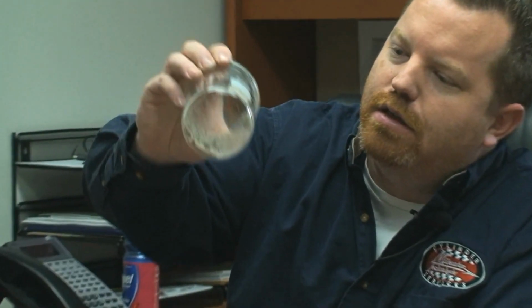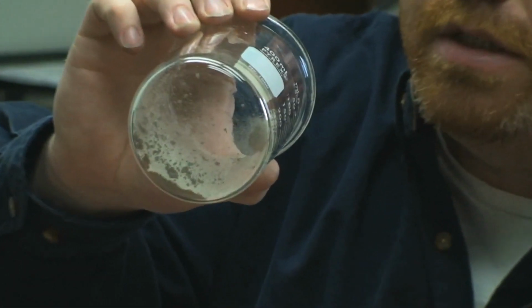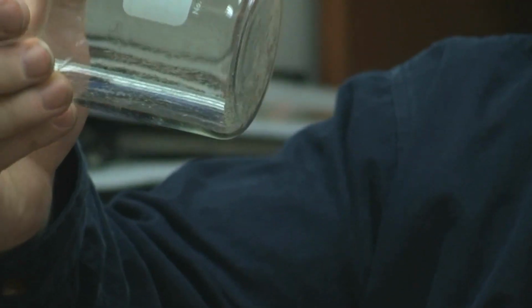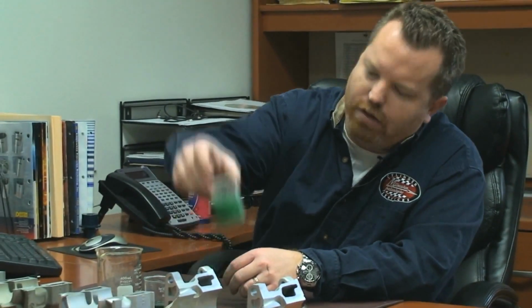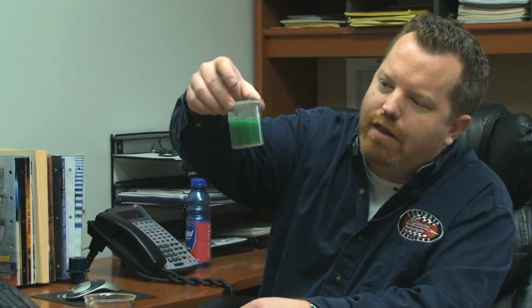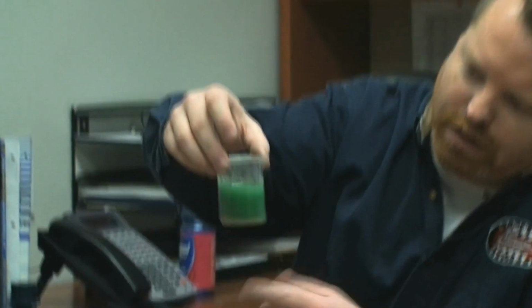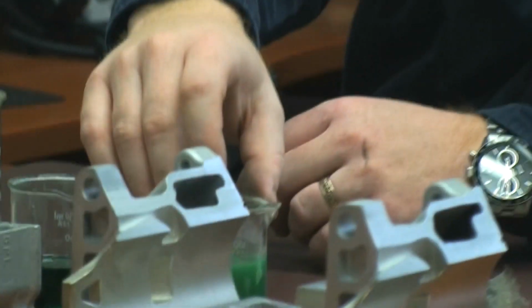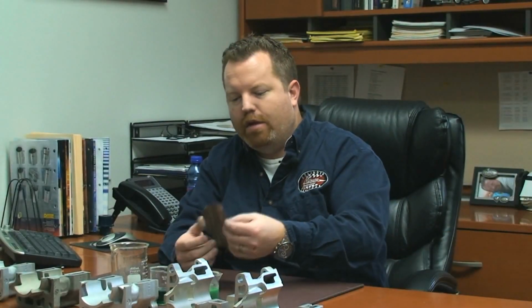Here I have some silicon carbide in the bottom of this. Not a lot of it. It's very expensive. It's 3 micron in size, so it's very small particles, almost like talcum powder. When you mix the two together, you get a bath that looks like this, and that's what our plating solutions look like. It's settling out a little bit, but that's what it looks like.